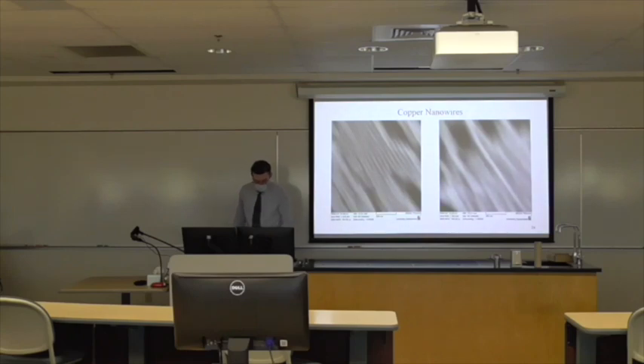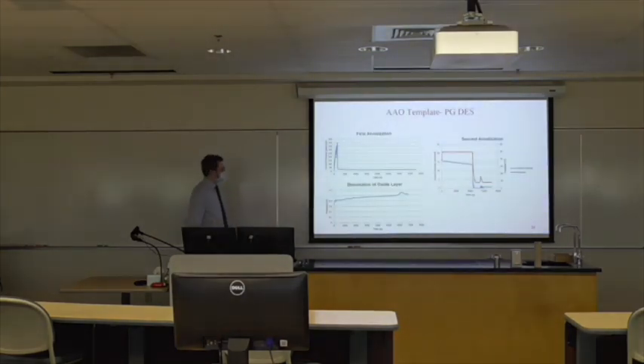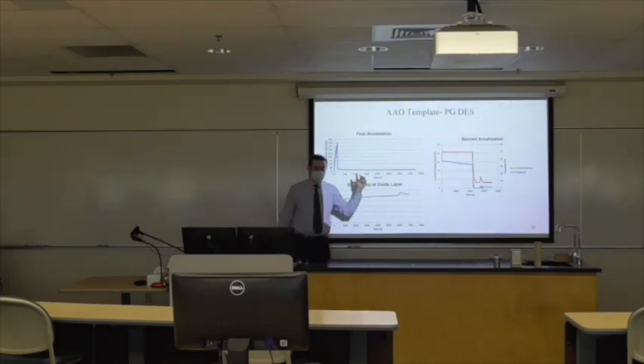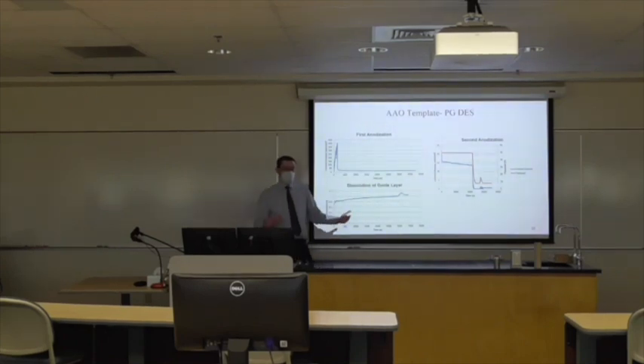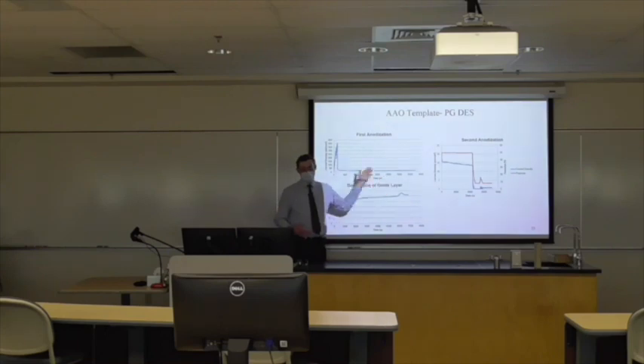So the actual production of the oxide layer, as far as the graph, there's this spike that you would expect in anodization, and it goes down to 15 milliamps per square centimeter. It lasts for an hour until you stop it. And if you change this time, you get a thicker layer, depending on how you want it. So you can simply let it go longer or shorter if you want a thicker or thinner layer, respectively.